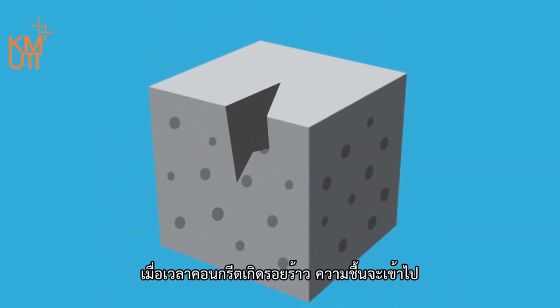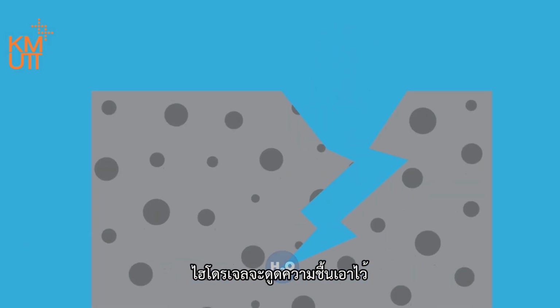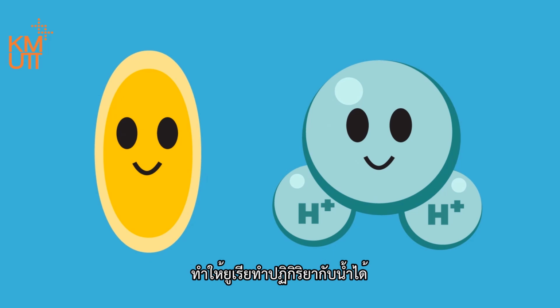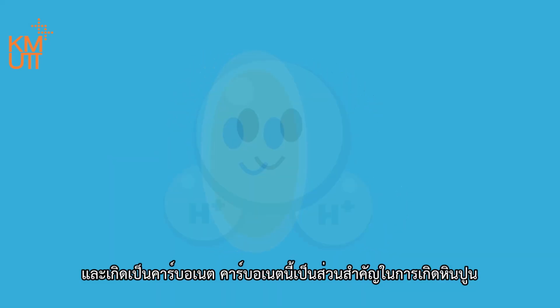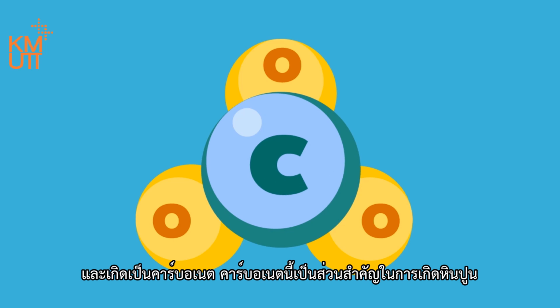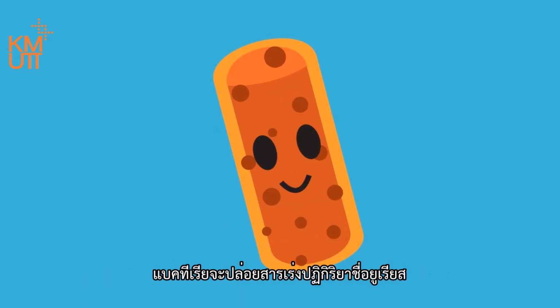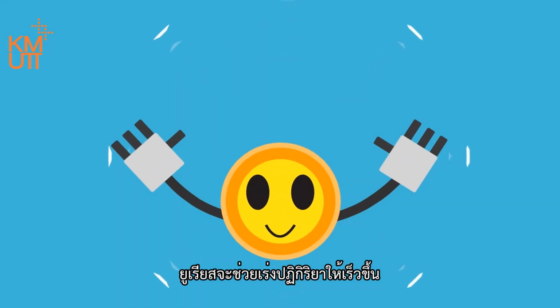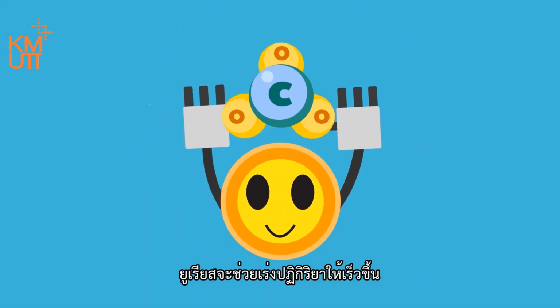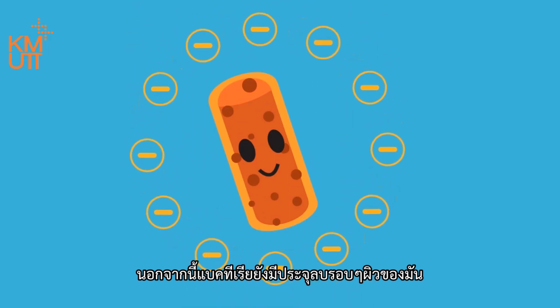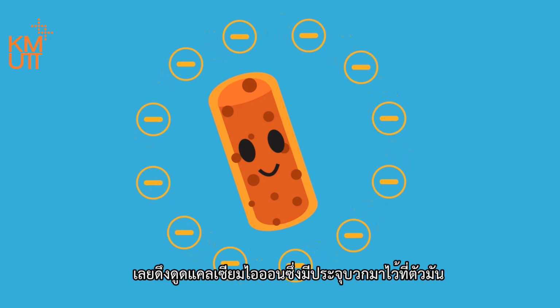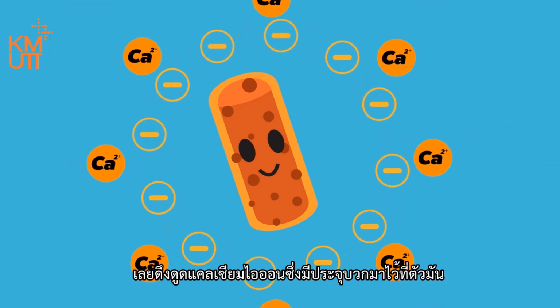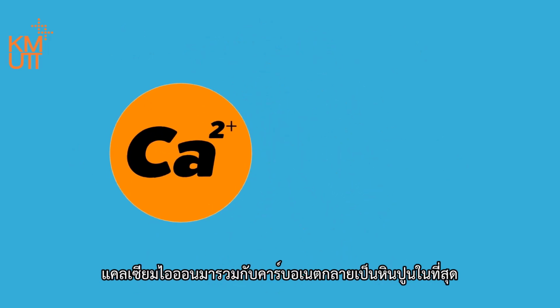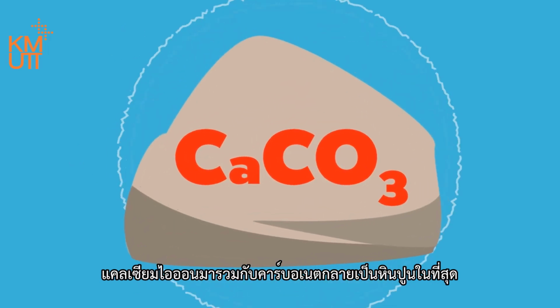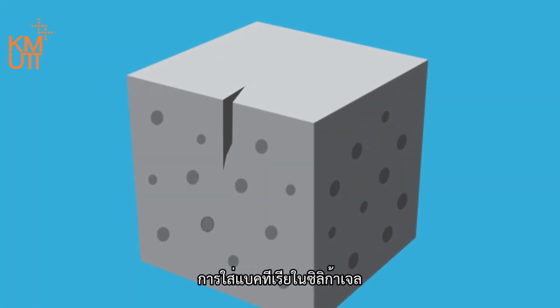When a crack occurs in the concrete, moisture would then be able to seep in. The hydrogel will absorb the moisture, making urea become reactive to water. This creates carbonate, which is an essential substance of limestone. Bacteria will release the accelerating chemical, urease. Urease will accelerate the reaction. Bacteria also have negative ions around them. They will attract the positive calcium ions, and now bacteria will be surrounded by calcium. Calcium ions combine with carbonates and become limestone. Limestone helps by filling the voids and healing the concrete.